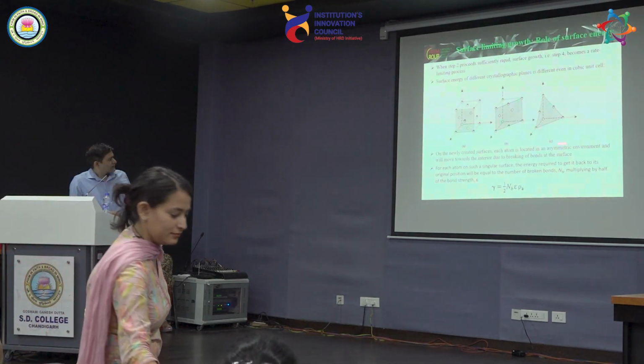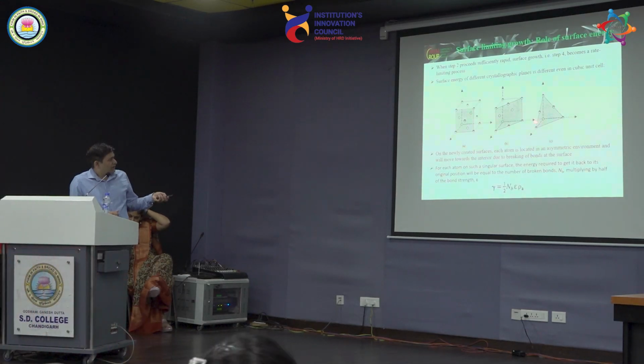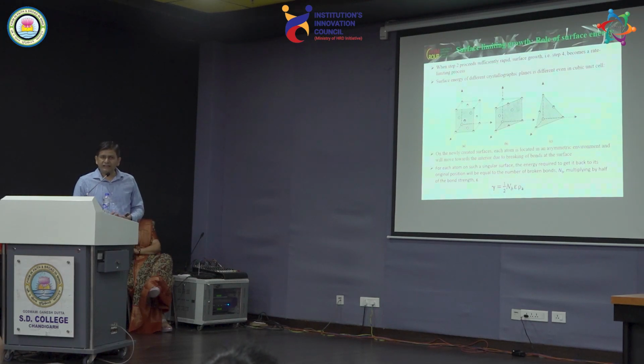Okay, so these are again basic things. When these vapors are condensing on the substrate, in which direction will they grow? That growth direction will be decided by the surface energy, and the surface energy for different planes, like suppose this is the 100 plane, this is the 110 plane, and this is the 111 plane, is decided by this formula, where NB is the number of broken bonds, epsilon is the bond strength, and rho A is the areal density, the atomic density on that particular plane.